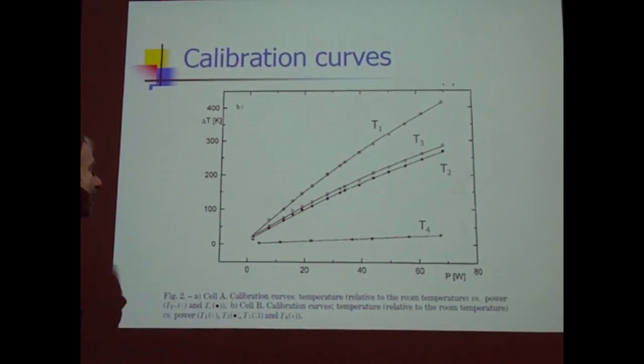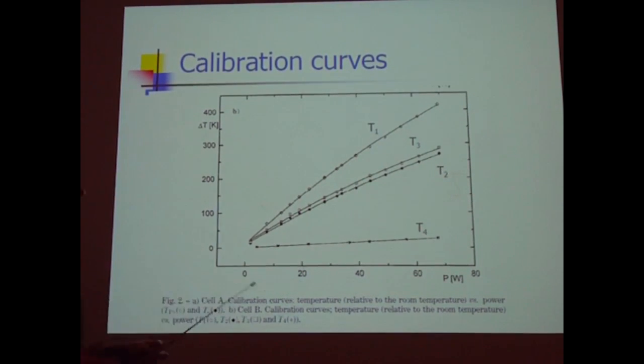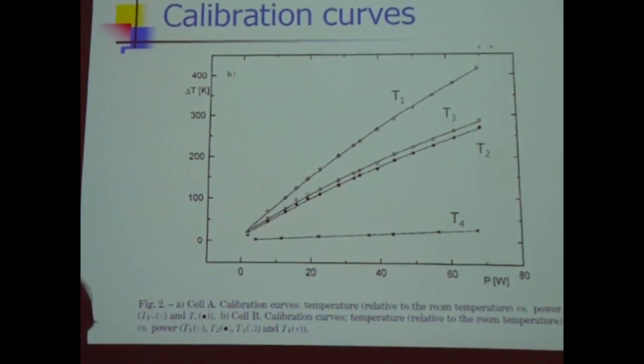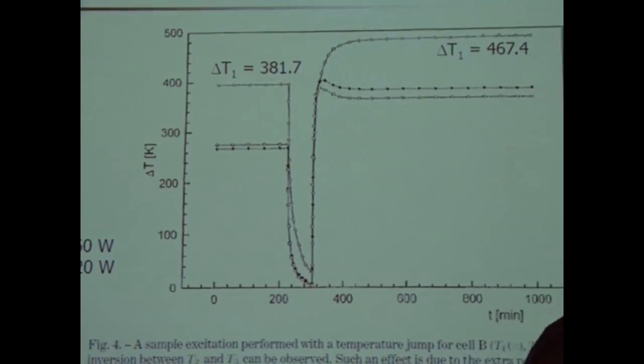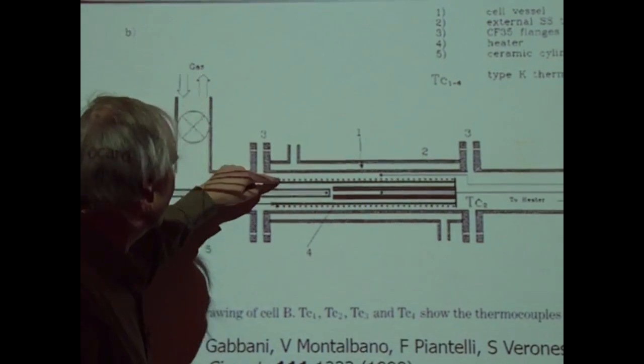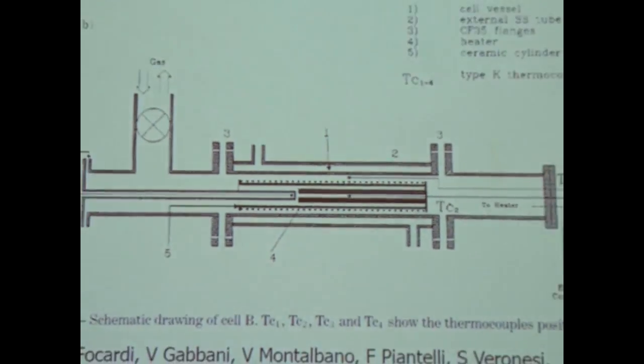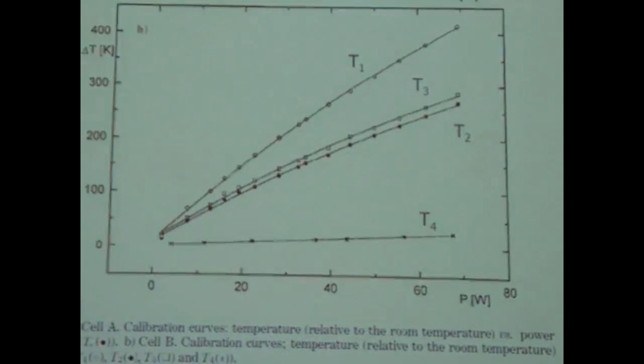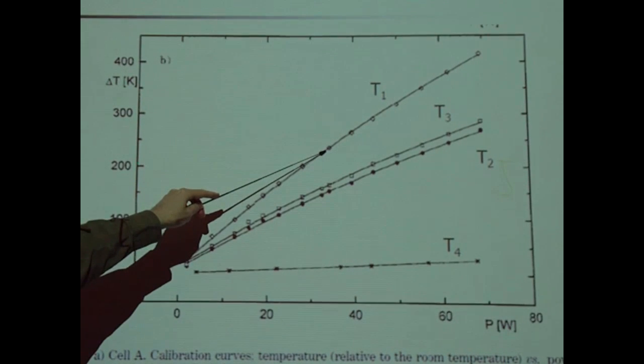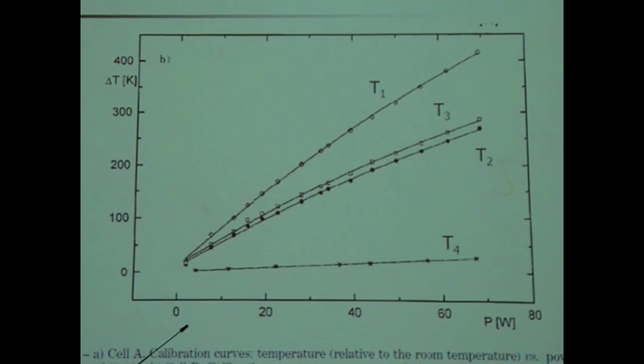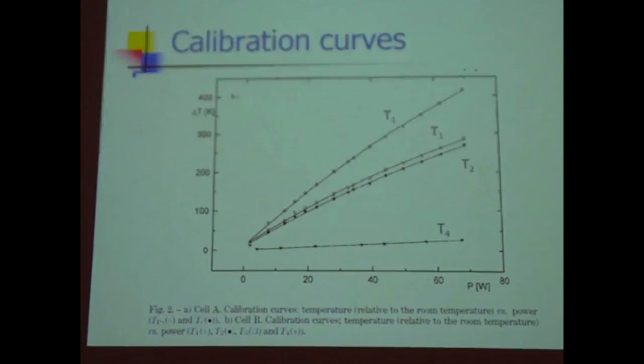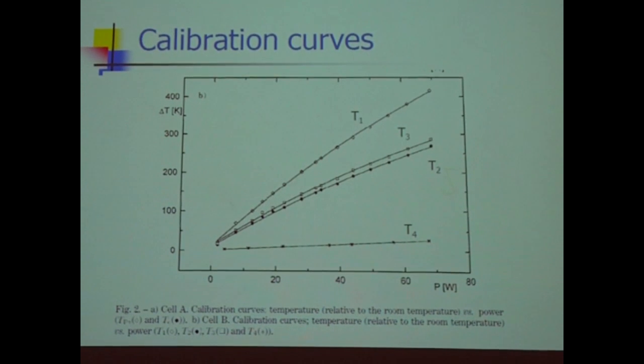So here's what the calibration looks like. TC4, which is away, you heat up. In the sample, there was a platinum heater. These guys right here, it's a platinum heater wrapped around, so you have to heat it up to get things to go. So what you see is that T1's closest to the sample, it's hottest, T4 is furthest away, it's much colder, so there's this giant temperature gradient in the system. According to some of the early discussion on this, that temperature gradient is a key feature of the experiment. When you do an experiment, you like to have isothermal conditions, and apparently this thing doesn't work with isothermal conditions.